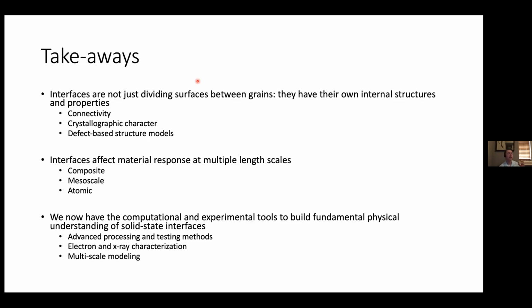So in other words, the more difficult it is to plastically deform a material, the easier it is to propagate a crack. And conversely, the softer a material is, the easier it is to plastically deform, the more difficult it is to propagate a crack. So there's this trade-off, and it has to do with what gives a material toughness. Especially in the case of metals, most of the toughness originates from plasticity occurring near the tip of a propagating crack.